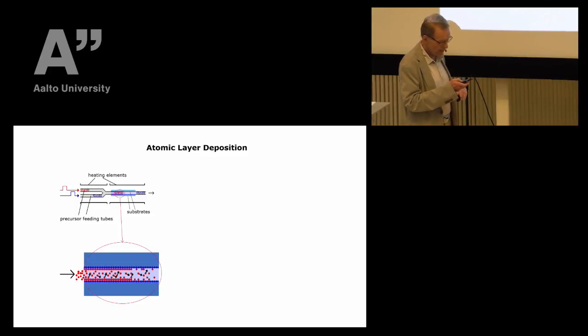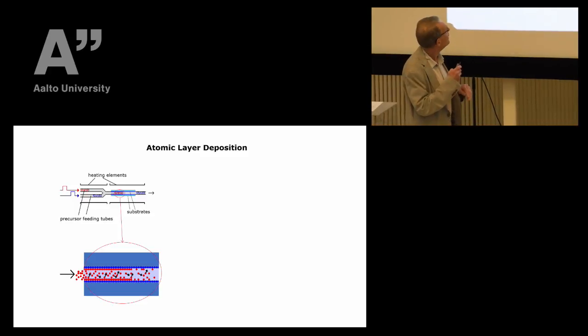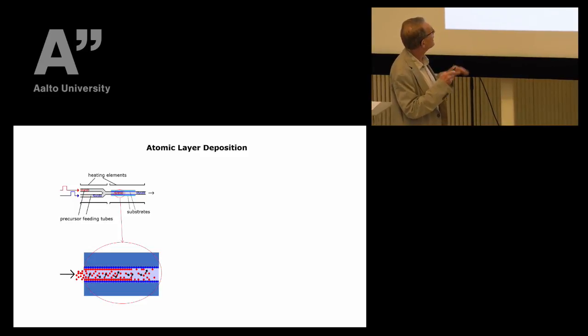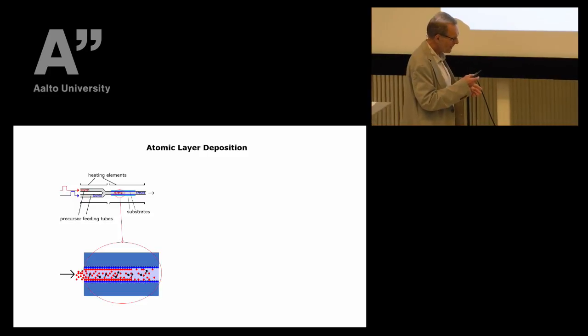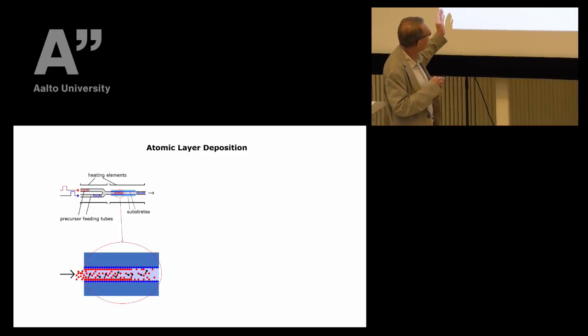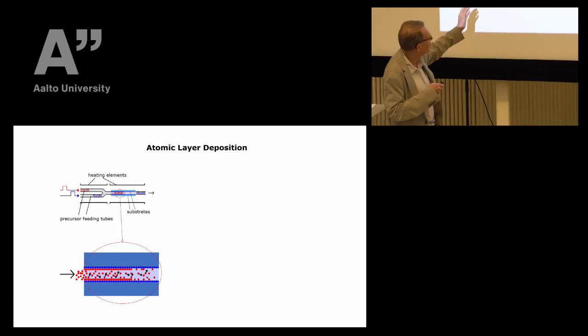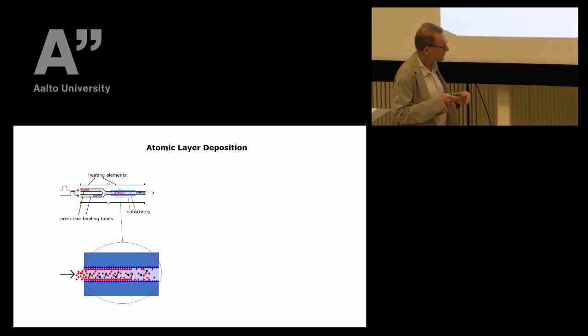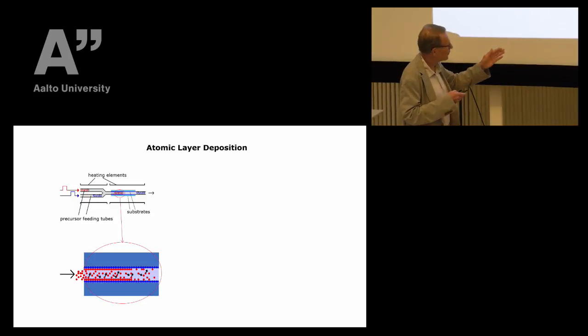Okay, so this is a schematic diagram of an ALD reactor. We are feeding the source material. Typically, a reactor is a gas flow reactor. So we have an inert gas flow at a low pressure, about 1 millibar or something like that. And one at a time, we inject the necessary source material, and they go through a channel or substrate. And you can see the big advantage here, which means that even the front end of the channel, the surface there gets far more material than the tail here. We get only one atomic layer.